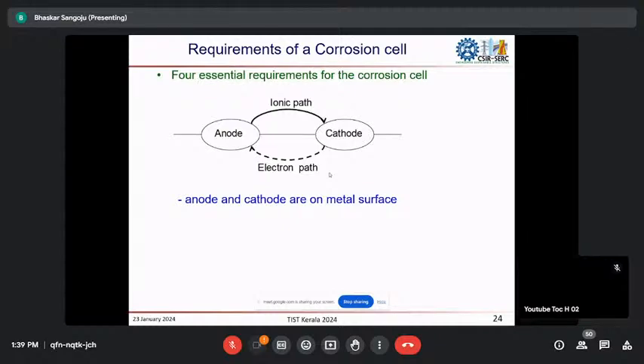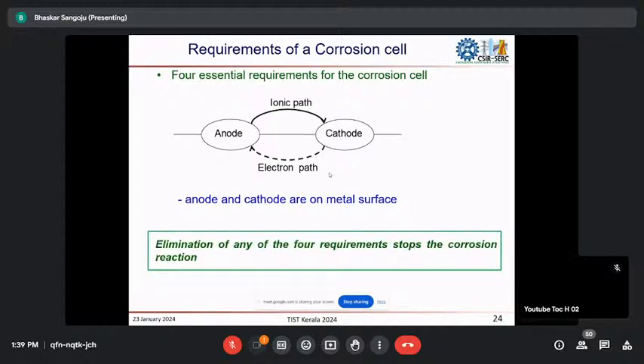So that is why if we make the concrete more impermeable and there is no oxygen availability, then we can very well protect the reinforced concrete structure from the corrosion deterioration. So elimination of any of these four requirements stops the corrosion reaction, so that makes the reinforcement bar better and better quality. That is why some people will go for stainless steel, epoxy coated steel, and galvanized steel. Thereby you are protecting the passive layer for longer durations.